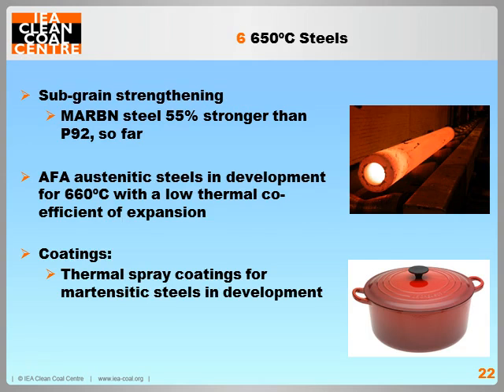New AFA Austenitic steels have a low coefficient of thermal expansion, which would allow them to be used in thick section components. They are being developed for use at 660 degrees Celsius. And also, coatings for Martensitic steels are in development. This would allow the use of existing, cheaper parent materials which are coated to use them at higher temperatures. Coatings are yet to prove effective, and boiler manufacturers have historically avoided them.